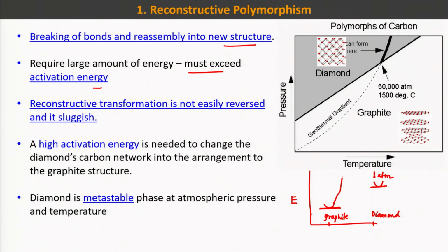If you see the graph, it is something like that. We know that diamond has an isometric structure, and the carbon is in 4-fold coordination, and we have learned about this. Diamond will be stable at more than 5 gigapascal pressure and 1500 degrees C. If you compare with a geotherm gradient, your diamond will be stable at this particular depth. So, when you bring this diamond to the surface, you decrease the pressure.